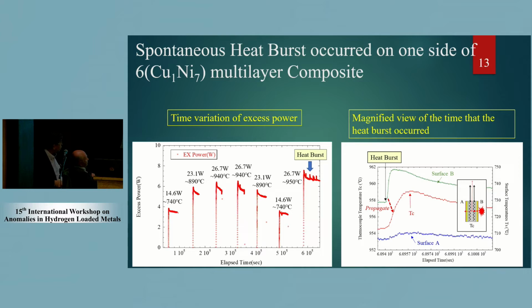The red line means the thermocouple in the center of the ceramic heater, green corresponds to surface B, and blue corresponds to surface A. In this case, at this point, a spontaneous heat burst occurred on surface B, and the temperature increased by about 20 degrees centigrade and propagated to the center thermocouple. Okay.